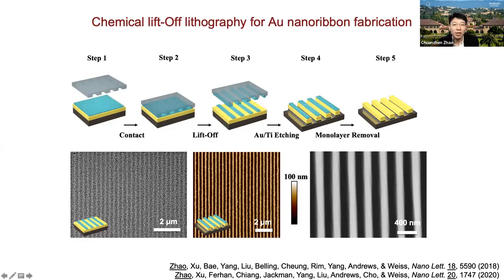This one is the SEM image of the patterned molecule on the surface. Those are just molecules patterned on the gold surface, alkanethiol molecules. And on the right, those are atomic force microscope (AFM) images and also SEM images of the gold nanoribbons. So we were able to pattern the gold nanoribbon arrays with 200 nanometer width and 400 nanometer pitch. We can use those gold nanoribbons as plasmonic sensors, as I will share with you in the following slides.